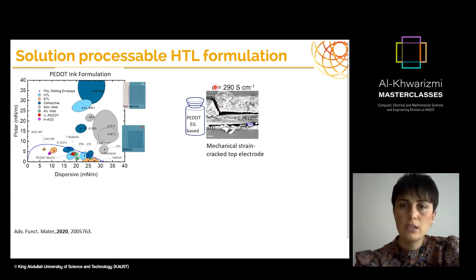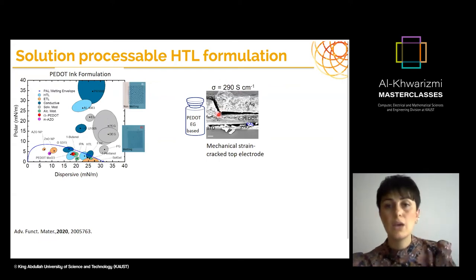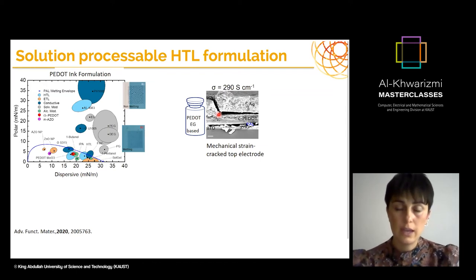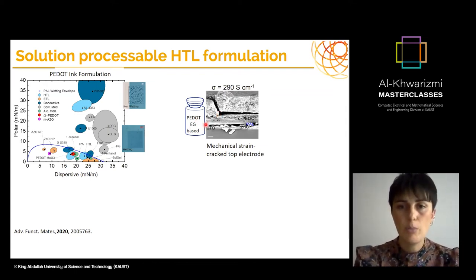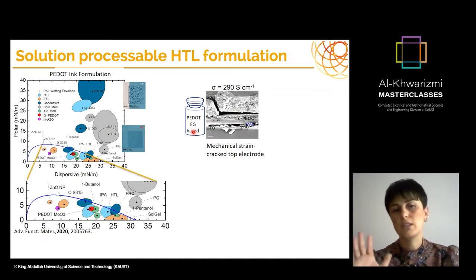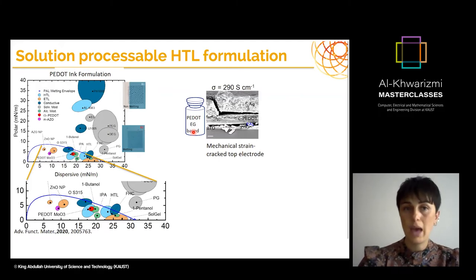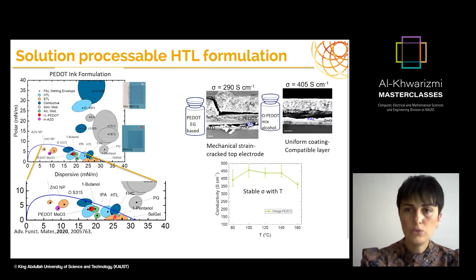And then obviously the conductivity was also decreased when we tried to further increase the compatibility between the photoactive layer and the HTL based on the ethylene glycol in this case. And then we realized that, okay, we really need to develop our own HTL and look for solutions. In this case, we moved to a PEDOT formulation mixed from alcohols, as you see, IPA or butanol or pentanol, which fits into this wetting curve, actually.